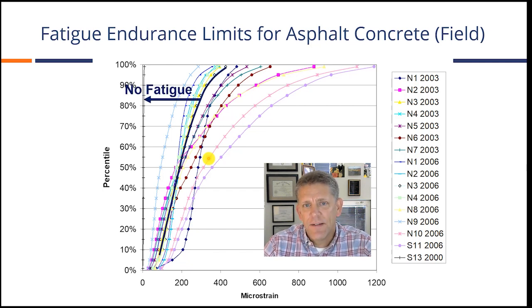And it doesn't have a whole lot of meaning until you know what the cracking history of these sections was. And what we found when we look at this family of curves is that everything on or to the left of this blue curve did not experience bottom-up fatigue cracking. You have a couple that are right on it. You have some that are further away, meaning they had lower strain. And then you even have one that's way over here. It almost looks like tick marks on this vertical scale.